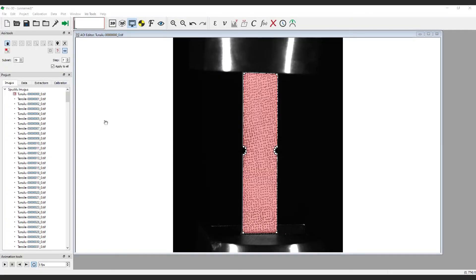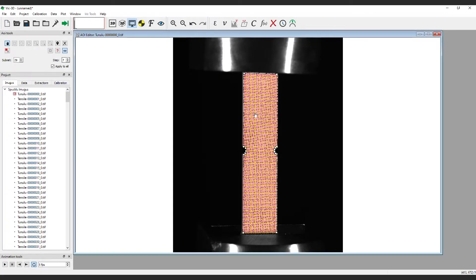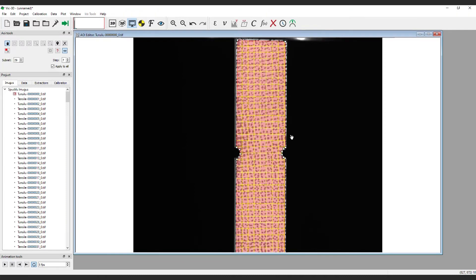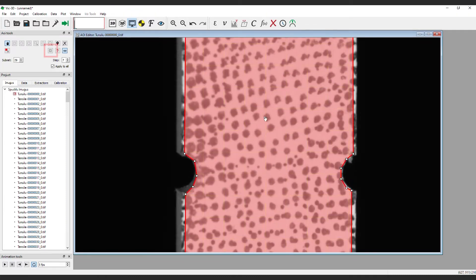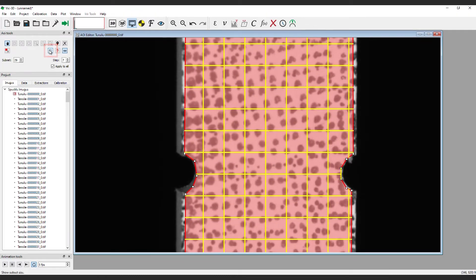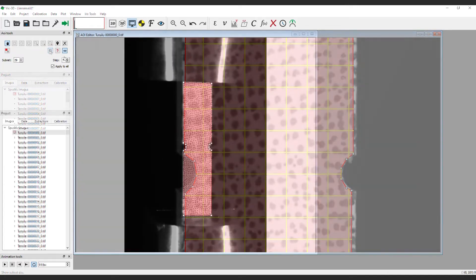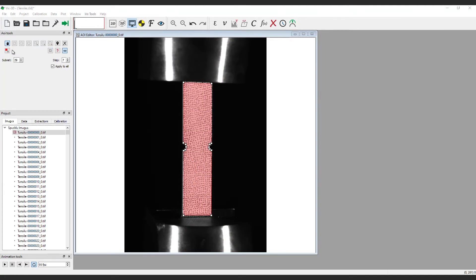The current size is illustrated by a grid briefly displayed on the AOI. You can bring that grid back up by clicking the Show Subset Size icon here. By default, VIC-3D starts with a subset size of 29 and a step size of 7.